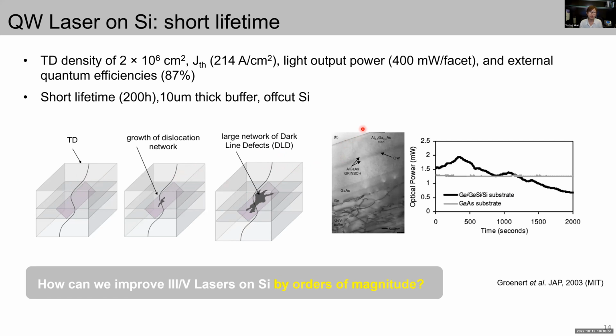So actually, research has been conducted since the 1980s to grow these quantum well-based lasers directly on silicon. Well, they have gotten quite a promising improvement in terms of threshold current density, light output power, and external quantum efficiency up to 87%, quite promising. However, the aging test shows the maximum device lifetime is only 200 hours. And this was even obtained with an ultra-low threading dislocation density of just 2×10^6, and that was obtained with a 10 micron thick growth of germanium, germanium-silicon, and silicon buffer, on an off-cut silicon substrate that is not CMOS compatible.